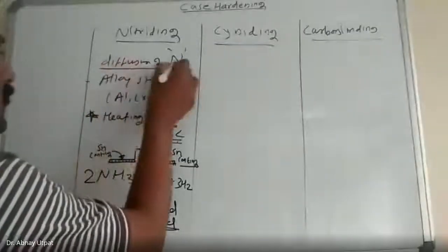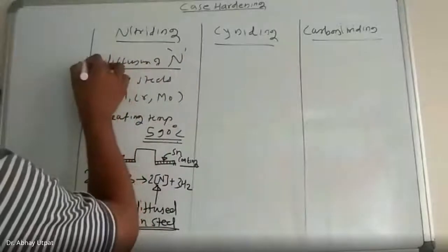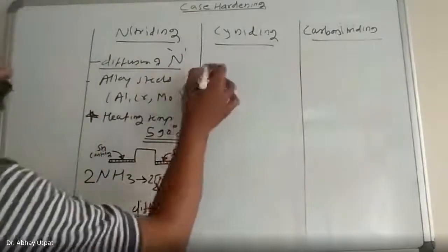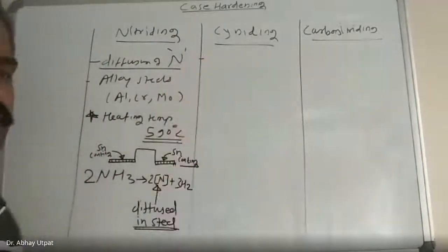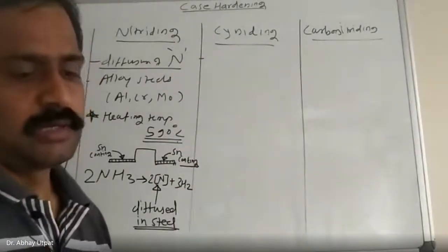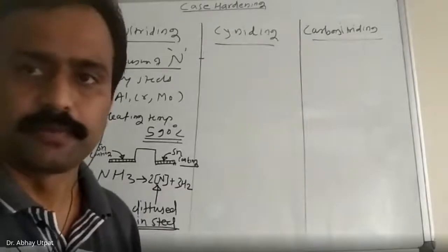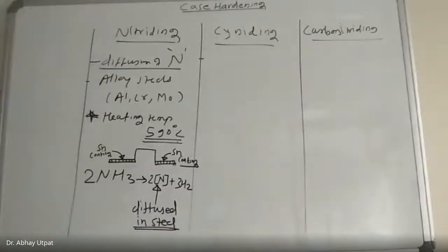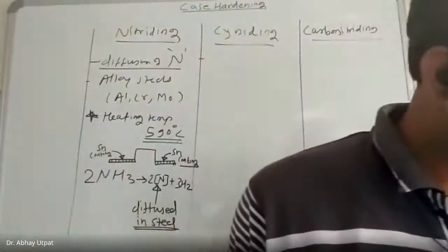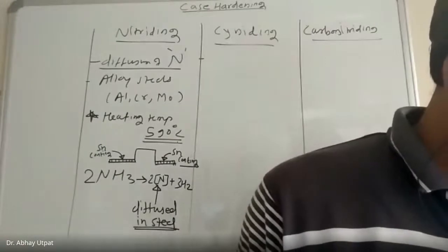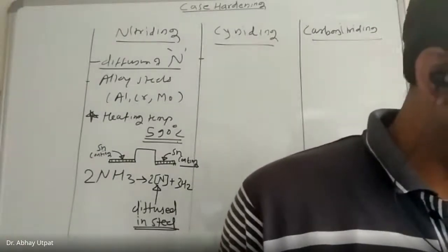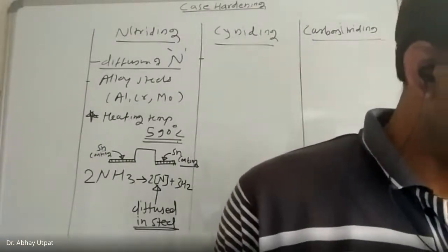For 0.5 mm case depth, the time required is 100 hours. Next slide.